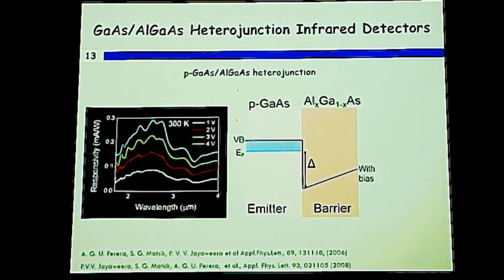We have these heterostructure layers, and above the active region and below the active region, we have highly doped contact regions, and we deposit metal contacts on those layers. On those metal contacts, we do wire bonding. From them, we connect a bias voltage from batteries.